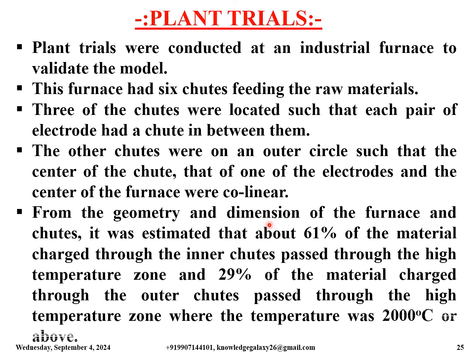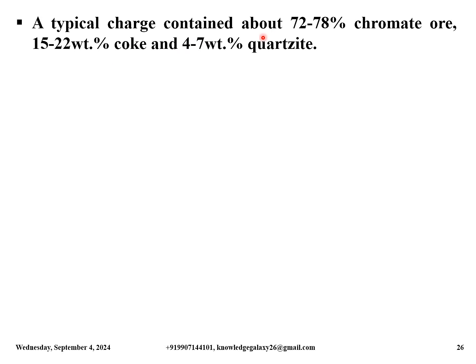From the geometry and dimensions of the furnace and chutes, it was estimated that about 61% of the material charged through the inner chutes passed through the high temperature zone and 29% of the material charged through the outer chutes passed through the high temperature zone where the temperature was 2000 degrees Celsius or above. A typical charge contained about 72 to 78% chromite ore, 15 to 22 weight% coke, and 4 to 7 weight% quartzite.